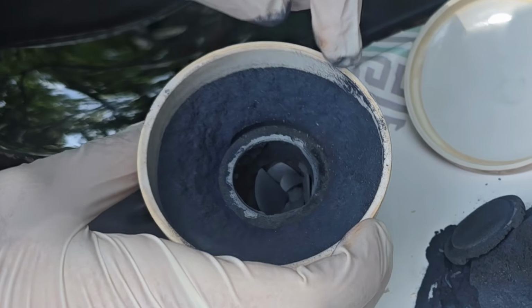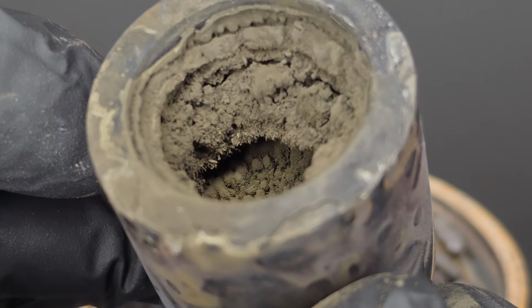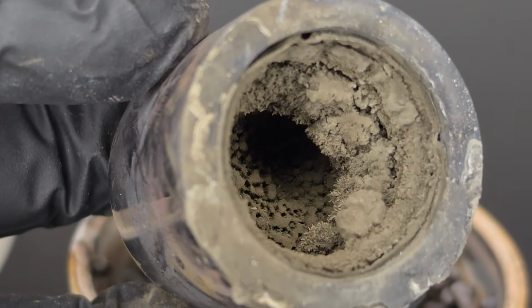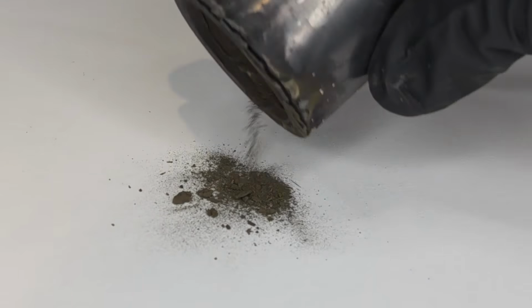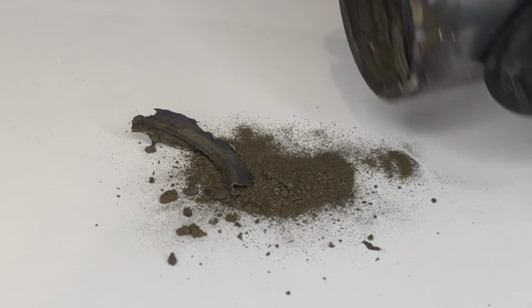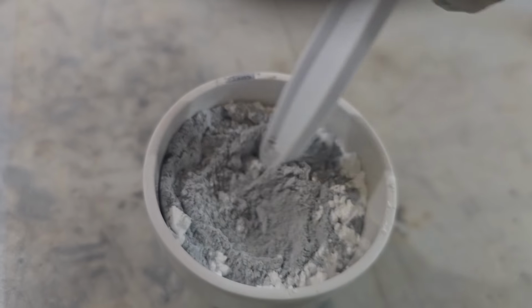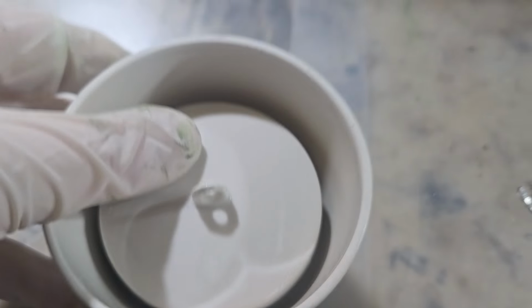And a couple of days later, I got a black crust. It turns out the charcoal also scavenged the oxygen right off of the molybdenum oxide, reducing it to molybdenum metal and leaving me with no rubies at all. So next I tried what I thought was an alumina crucible. Alumina is just more sapphire, and it should contain the flux long enough to grow rubies in it.